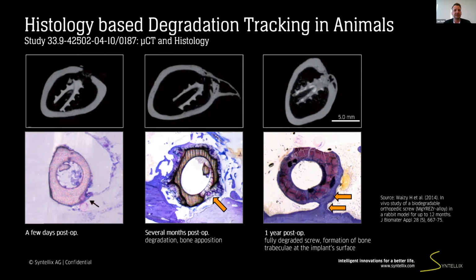With animal trials, it could be impressively shown that magnesium-based implants actually turn into bone. While a few days post-surgery, the implant structure did not change significantly, as can be seen in a cross-section of a histology in the first image, the implant biodegrades and is penetrated by bone cells in a follow-up period of up to 1 year in this example.